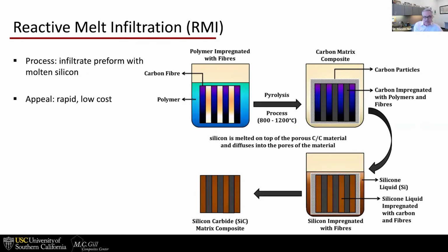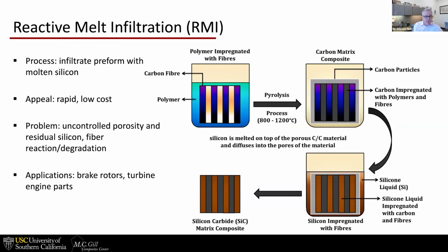The appeal, and that's a big one, is particularly low cost. The cost of these process routes is generally quite high. This is probably one of the lowest cost routes. And the challenges: the porosity is not very well controlled, nor is the composition, and particularly residual silicon. Silicon is a low melting component in this assembly, and that's going to be a problem. It's difficult to get all of the silicon to react to silicon carbide.